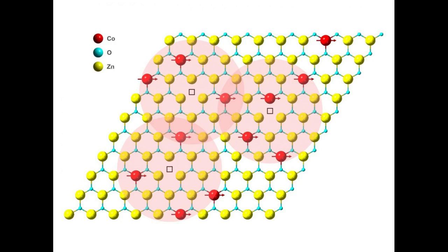The researchers synthesized the new 2D magnet, called a cobalt-doped van der Waals zinc oxide magnet, from a solution of graphene oxide, zinc and cobalt. Just a few hours of baking in a conventional lab oven transformed the mixture into a single atomic layer of zinc oxide with a smattering of cobalt atoms sandwiched between layers of graphene. In a final step, graphene is burned away, leaving behind just a single atomic layer of cobalt-doped zinc oxide. It is potentially scalable for mass production at lower costs.